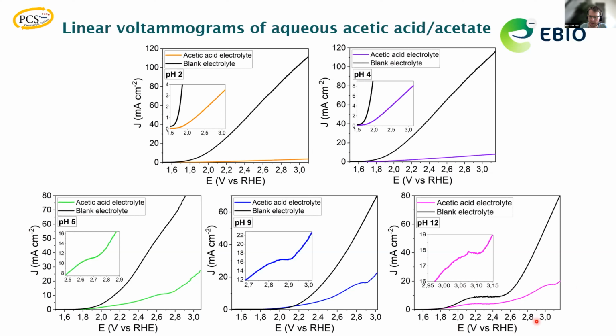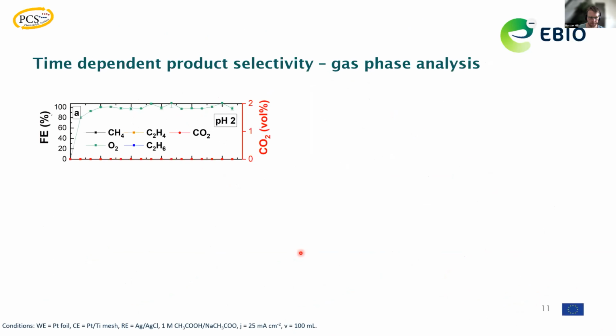A peculiar thing here in this pH 12 electrolyte is, of course, this kind of double transition region, but this is just a change in water oxidation mechanism, and the actual plateau transition region to Kolbe oxidation only occurs here at around 3 volt. So we were already quite sure that in low acidic or in high acidic conditions, we do not have any Kolbe products forming, but we will detect Kolbe or non-Kolbe products in higher pH conditions.